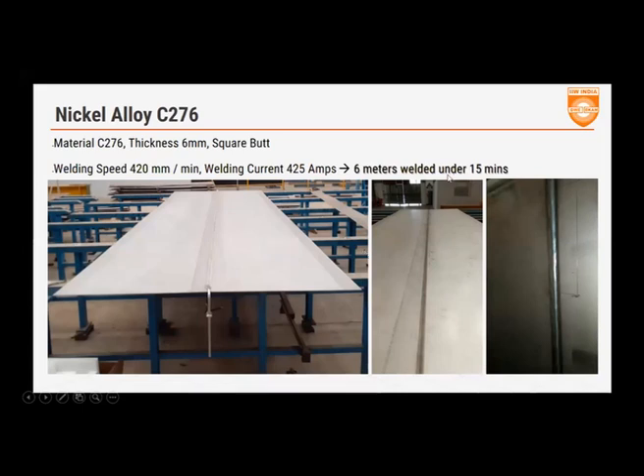I hope I'm stressing this point enough. They welded a 6 meter long joint, 6 mm thick, in a single pass under 15 minutes. You can see the penetration on the other side, and this is where you had the top layer. If you wanted to cap it, you could have one more layer on top to do a capping because this will give you a flush or near flush finish. If you wanted to add one more layer with filler wire, it would still have taken you much less time to do the job.